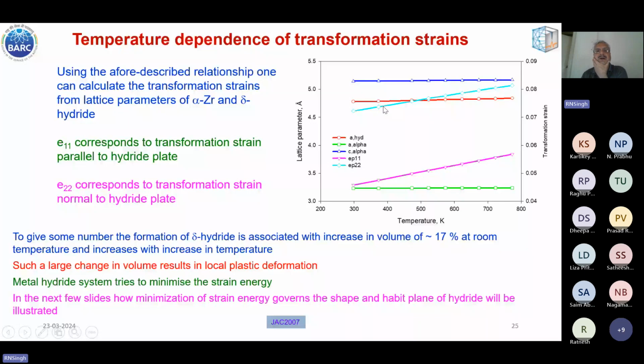Using this, one can calculate the accommodation energy of hydride in the matrix. To give some numbers, the formation of delta hydride is associated with an increase in volume of about 17% at room temperature, increasing to about 20% at 300 degrees Celsius. Such a large change in volume results in local plastic deformation. The metal hydride system tries to minimize the strain energy. The next few slides will show how the minimization of strain energy governs the shape and habit plane of hydride.